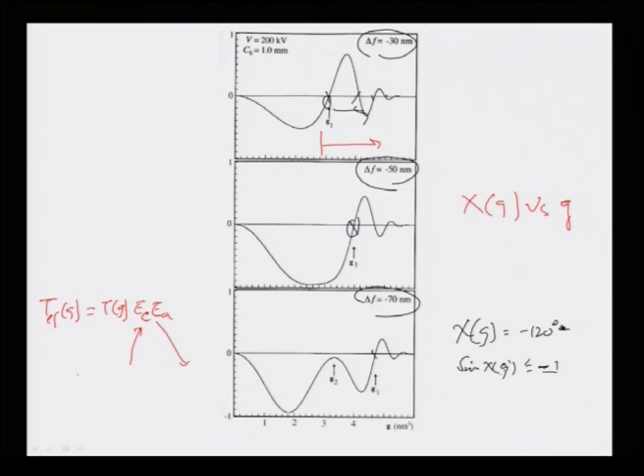E C is basically due to chromatic aberration, and E A is due to spatial coherence of the electron beam. Once you put this envelope function into the transfer functions, they come in as multipliers, as you can clearly see, and this gives us a limitation on using higher values of g in the transfer function. This effectively means the envelope function is acting as a virtual aperture in the back focal plane of the objective lens, regardless of the value of the defocus. That is the actual meaning of that.